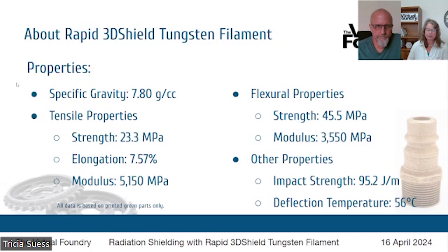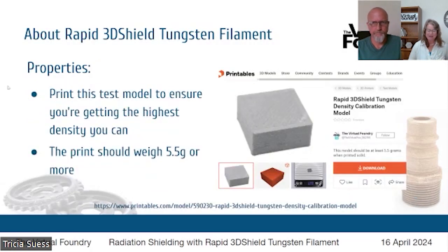Now, the properties of the Rapid 3D Shield Tungsten Filament, you'll see some of those listed here. These properties or these tests were performed on printed tungsten parts. They're also reported on a printed green part, so no debinding or sintering activity has been performed on these parts. Now, due to parameter settings or changes in the methods used between printers, these specifications can't be guaranteed on printed parts that you make yourself, but we do have a test that you can perform to make sure your print settings are optimized and you're getting the most out of your filament. So if you were taking in that data on the prior screen, all of that is listed on the rapid3dshield.com website. So you'll see all of those listed there.